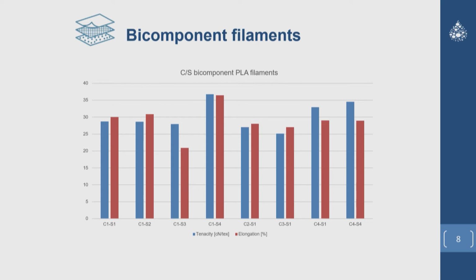But there we see that it's more difficult to process it, even though we would expect a higher tenacity, since you have crystals in both the sheet and the core reinforcement. But it was more difficult to process them, and if you want to make a composite out of them, you need to make sure that you have a temperature window that you can use, so only your matrix material melts, but not your reinforcement. So a combination of two semicrystalline PLA grades, it's not really possible for the processing into